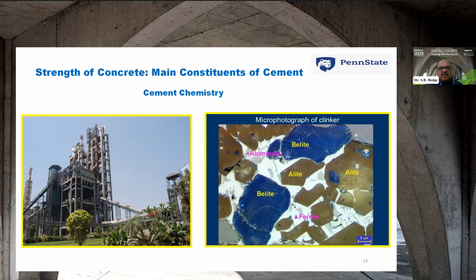Another photograph shows the micrograph of a polished sample of a clinker, which shows the alite, belite, aluminate and ferrite. These four phases are responsible for the strength in the cement.